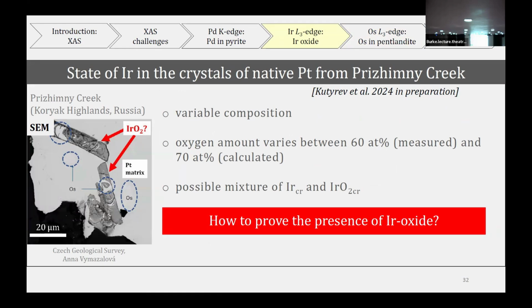Okay, so just to understand, I think the problem, especially when you give the percentages or the possibility to divide the iridium in the 2 phases, is related to another possible artifact about the depth of interaction of your technique. You say 10 microns, right, for the size of the crystals. But what about the depth of interaction of these energies, it will maybe even be 30 microns. So you are thinking that your phase is homogeneous down to that point. Well, I was not aiming for not touching the matrix, because it's impossible with a 60 micron beam. It's impossible not to touch the matrix around these microcrystals.